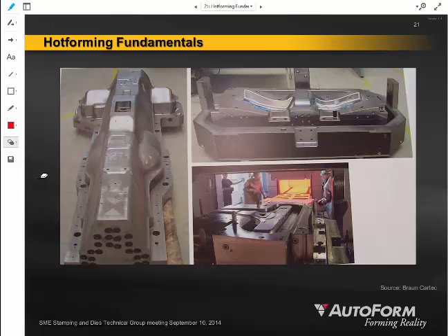So they heat the whole blank up, and then at the tail end of that furnace, they've got a steel plate hooked up to a massive heat sink that will draw out a bunch of that heat right as it exits the furnace, and they use this selective cooling to cool the blank down. Now, there's a lot of R&D going on right now, exactly as you mentioned, Bob, of trying to use more selective heating techniques like induction. If you could build a better induction heating method, you could only heat the areas that you wanted to heat and just leave the rest of the blank cool.